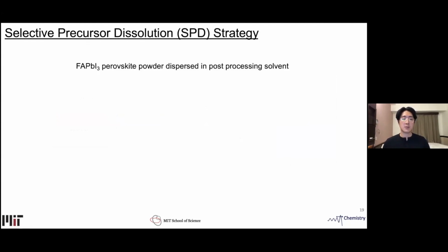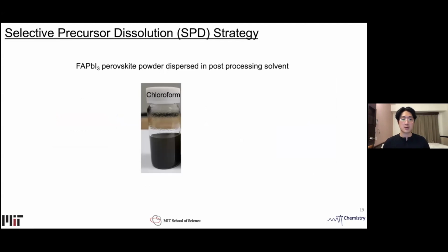Here I'm going to demonstrate its effect by showing a photograph of formamidinium lead iodide perovskite powder dispersed in two different post-processing solvents overnight. On the left is the powder dispersed in chloroform, and you see it retains its black color, meaning it hasn't undergone chemical decomposition or phase change.